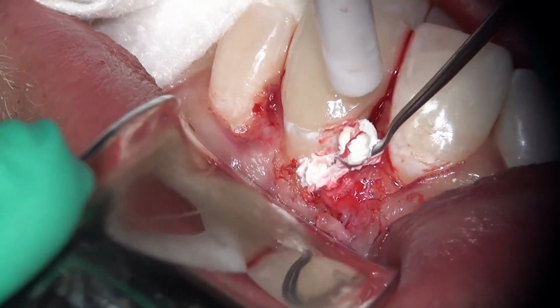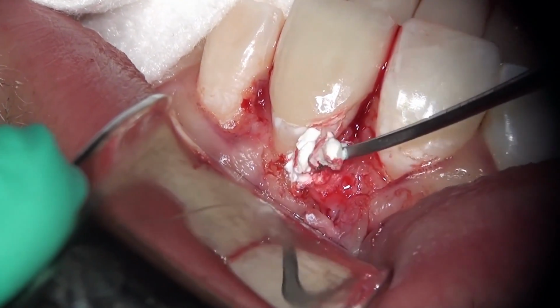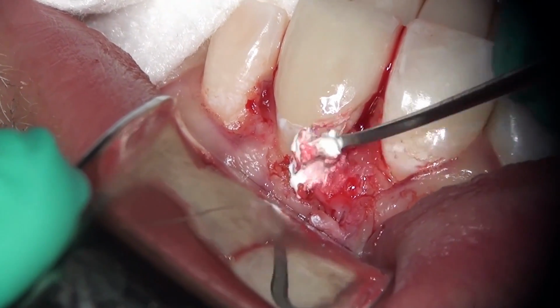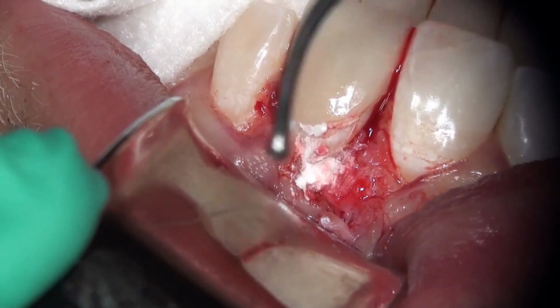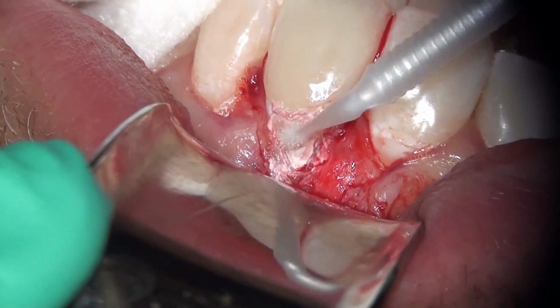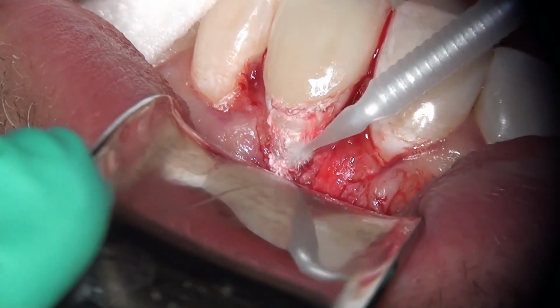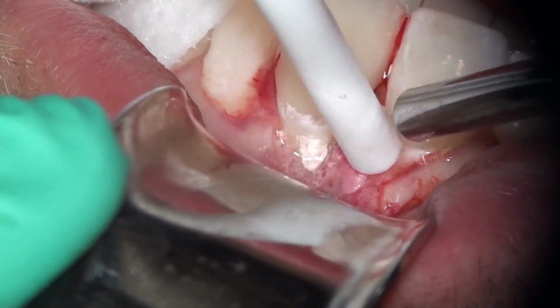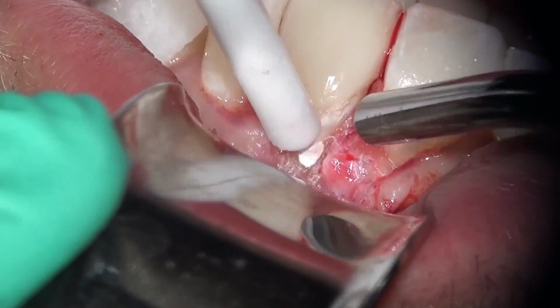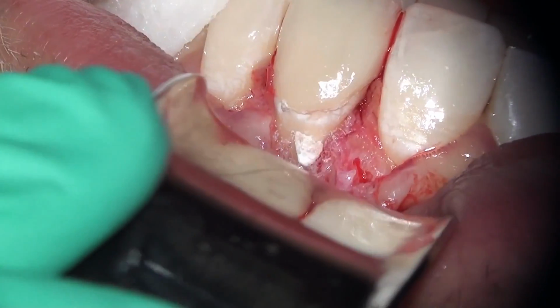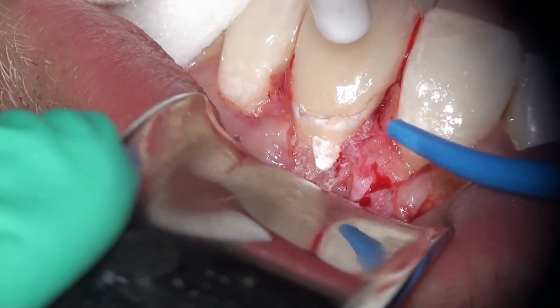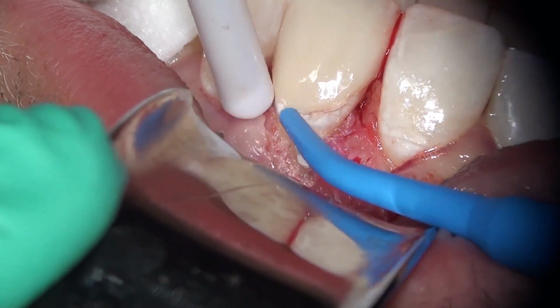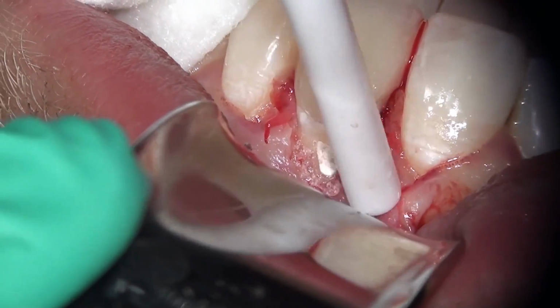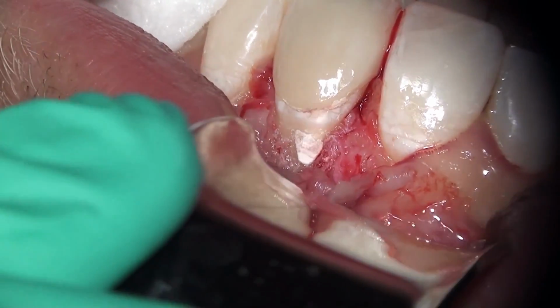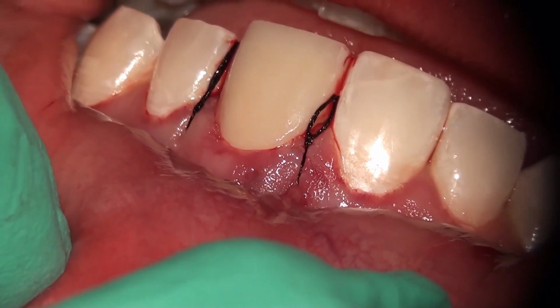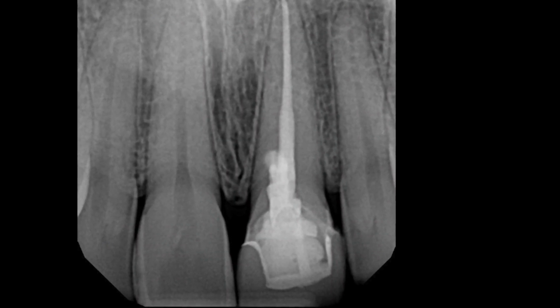So anyway, now that we have placed the putty in place, this is the lid technique, and the lid is keeping the syringeable material safe, and it allows for the material to set. Then use a micro brush to loosen up the flash, and then water to rinse out any of the remaining flash in the area. Dry it. And in this case, you can see these were veneers that were not done very nicely for this patient. There's that gap that always will create a little bit of marginal gingivitis.